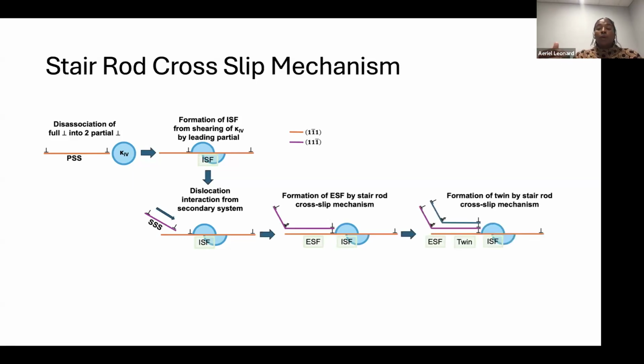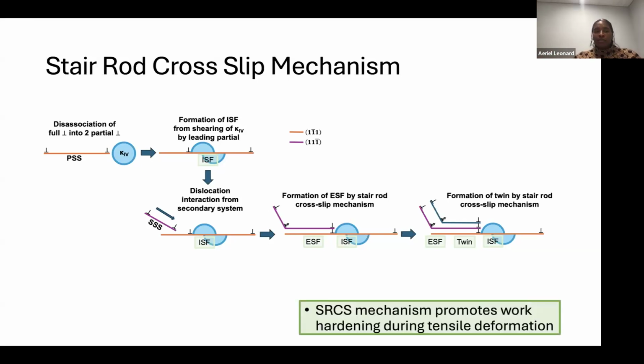As we keep going at high levels of strain, we have more slip systems to be activated. So now we have another partial that's interacting with the extrinsic stacking fault and forming a three-layer twin. And so this is something that has been reported in TWIP steels as a way to form deformation twins from stacking fault formations in the material. And all of this is really important because this is a hardening mechanism.